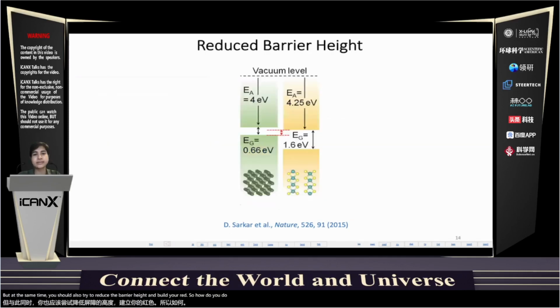So how do we do that? To reduce the barrier height, the energy barrier height, we can judiciously choose the different materials. In this case, I have chosen germanium as the 3D material and molybdenum disulfide as the 2D material. These materials are chosen because among the most commonly known 3D materials, germanium has relatively low electron affinity and low band gap. And molybdenum disulfide has slightly higher electron affinity.